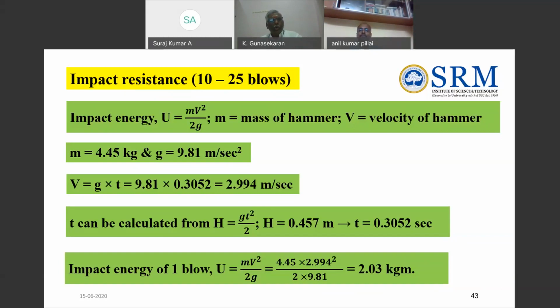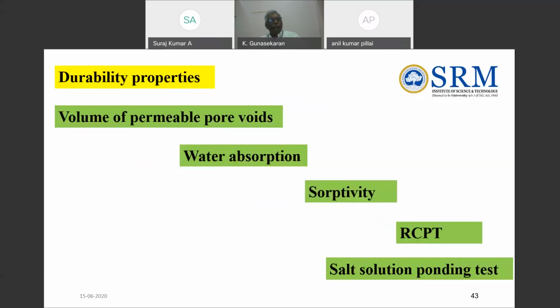So from that we know the mass of the weight. We know the velocity now. We know g also now. So from that, for one blow, the energy can be calculated at the end. For one blow, it is equal to 2.03 kg meter. That is the energy absorbed by your concrete. So the number of blows your concrete takes for initial crack multiplied by 2.03 will give the energy absorbed by the concrete in terms of impact resistance.